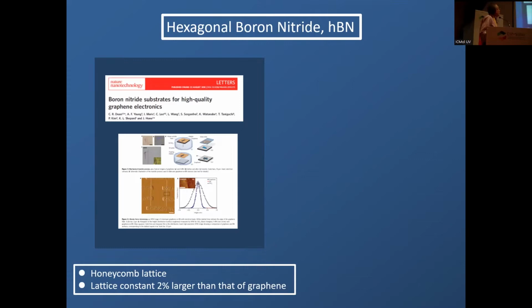In this paper in 2012, it was discovered that boron nitride, which is a well-known wide gap insulator, monolayers, or systems with a few layers, were perfect for encapsulating graphene, in such a way that graphene preserved very well its very nice transport properties and so on. And after this paper, everything changed in the study of graphene and other 2D materials.